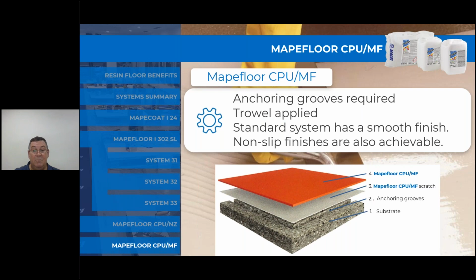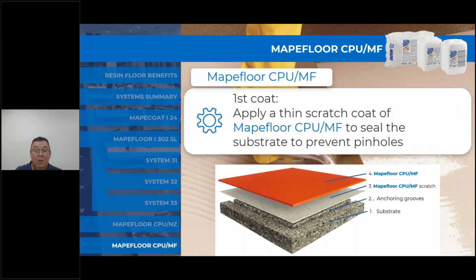So the standard system has a smooth finish, but it can also have a non-slip finish. So broadcasting into the Mapefloor CPU MF, a second coat can also occur, and in that case then a top coat is required to seal it off. So applying a thin scratch coat to seal the substrate and to prevent any pinholes.